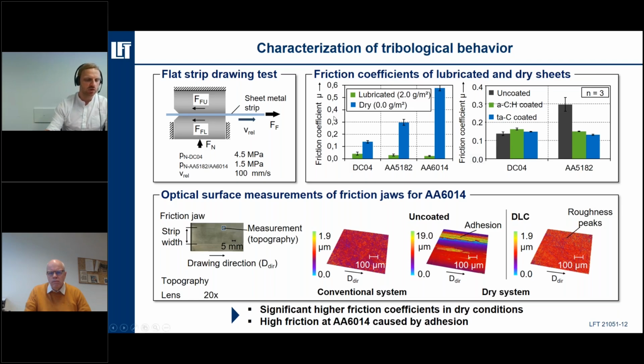At first, the reference strip drawing tests were carried out for deep drawing the steel DC04 and two different aluminum alloys, the AA5182 and the AA6014, with a sheet thickness of 1 millimeter. The first experiments have been conducted under lubricated, the green ones, and dry conditions, the blue ones, to gain a basic knowledge of the impact of lubrication in deep drawing processes. You can see that the values of the friction coefficient vary between 0.03 and 0.59, depending on the lubrication and the sheet metal material. Without the use of lubrication, we gain much higher friction. This is no surprise, but we see at first that our testing works.